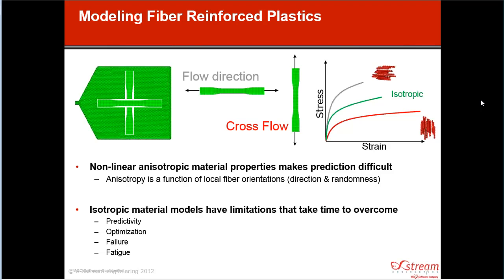In the second scenario, where now we're going to load the material transverse to the direction of how that part was injection molded, so the flow direction during the injection molding, we're going to see a response that looks more similar to the red curve there, where the material is going to be less stiff in the beginning, and then it's going to go into plasticity much sooner. It's going to be much more ductile, so you're going to have a much higher strain and lower stress at failure. So very different material response for those two different loading scenarios. And really what we're seeing there is the effect of the local fiber orientation on the material.